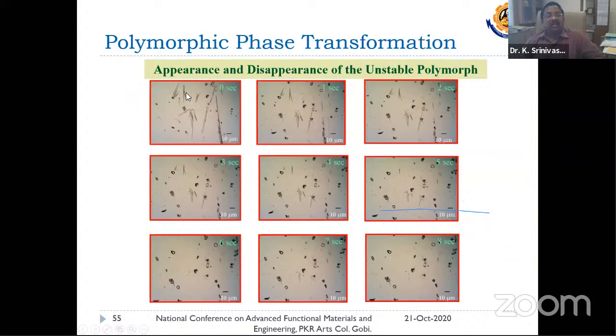The needle-like forms are unstable, whereas the smaller columns are monoclinic. So it's only 8 seconds. This unstable nucleation completely dissolved, while the other, monoclinic, is continuously growing. So that is the beauty. One has to carefully design the crystal growth parameters to capture this.